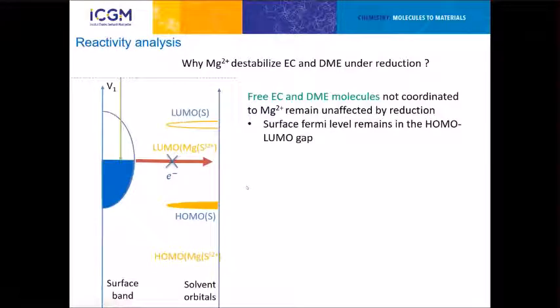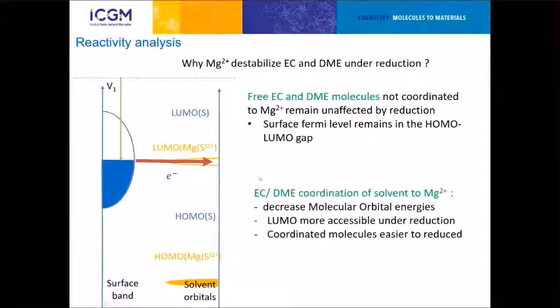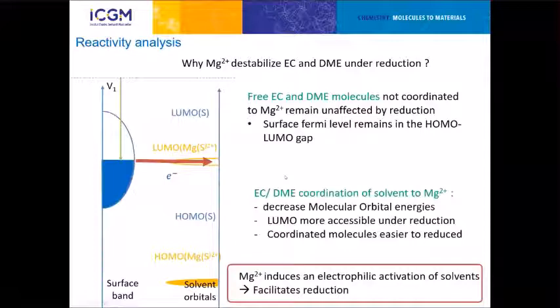But when we coordinate the solvent molecule to magnesium, the effect of magnesium on these molecular orbitals is to shift down all these orbitals. In particular, the LUMO is shifted down, and it can be shifted down into the range of reduction of the surface. So because of the attachment to magnesium, some of the attached solvent molecules are going to be reduced and can undergo this reduction that will lead to either dimerization or fragmentation. So one of the problems of the magnesium 2+ is that it creates some kind of activation of the solvent molecule. It's very close to what is observed in organic chemistry, some kind of electrophilic activation that facilitates the solvent molecule's reduction. That, in fact, is really the problem. Solvent alone is stable, but when it's coordinated to magnesium, it becomes sensitive to reduction.